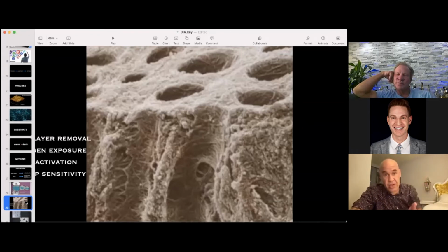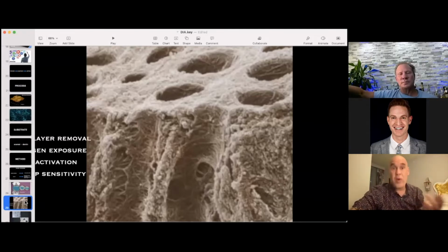Okay, so how do you achieve proper moisture? After you etch, you rinse. After you rinse, you use high vac. That's your proper moisture right there. You're going to see a shiny dentin. Your collagen is going to be hydrated and it's ready for you to place your adhesive, whatever adhesive you want to use. It doesn't matter. But now your adhesive is going to be able to penetrate through the collagen and seal the tubules. The problem when you open up the tubules is that there is this article.